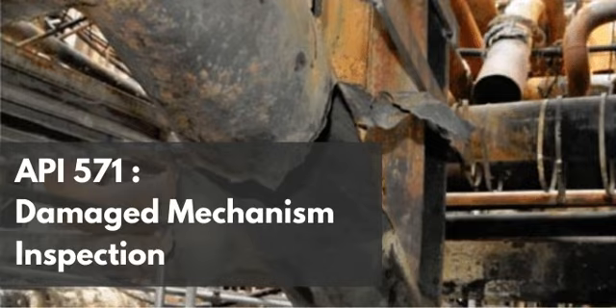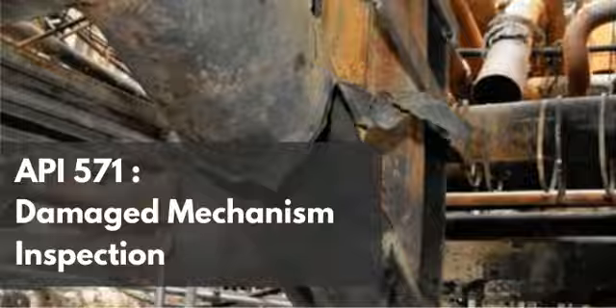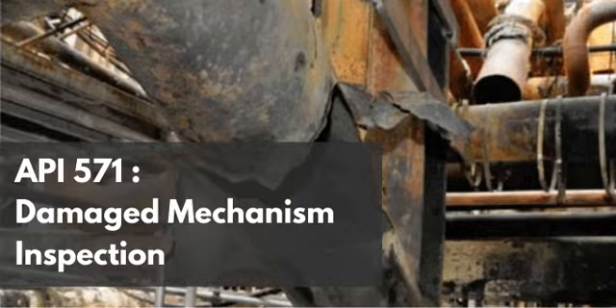Here is the paradox. The localized corrosion at the weld creates such a deep, incredibly sharp groove, remember, carving out half the thickness of the metal with almost vertical walls? Right. Because the geometry of that corrosion canyon is so sharp and so deep, when the shear wave UT sound wave hits it, it acts exactly like a crack. The sound bounces straight back.